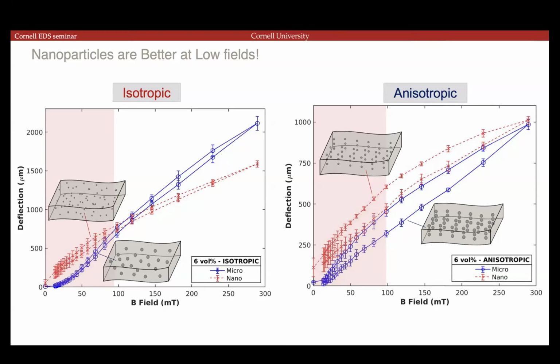Originally, what we want is that the anisotropic films, if they're all chained up properly, then you reinforce the magnetization. So these are interacting magnetic particles, and you have a larger magnetic moment along that direction. So we increase the magnetic moment, and then that should respond more to a gradient and deflect towards a field. But then also it's responsive to an orthogonal magnetic field.